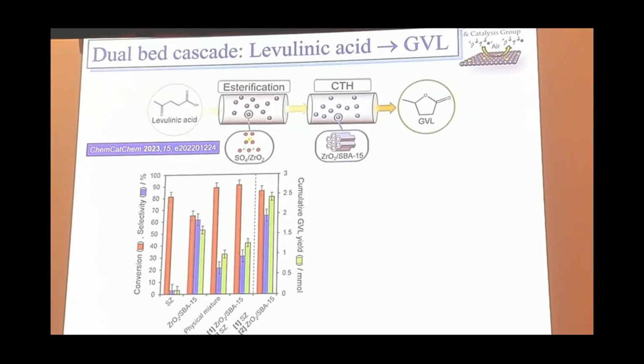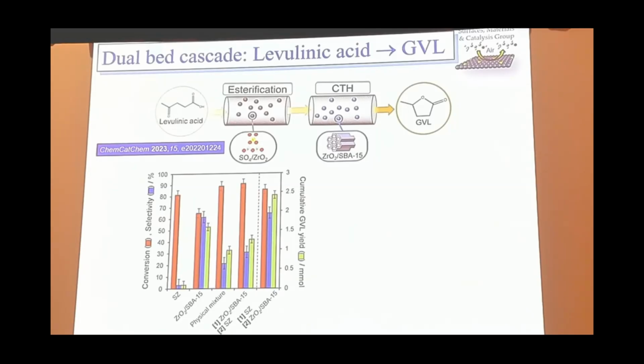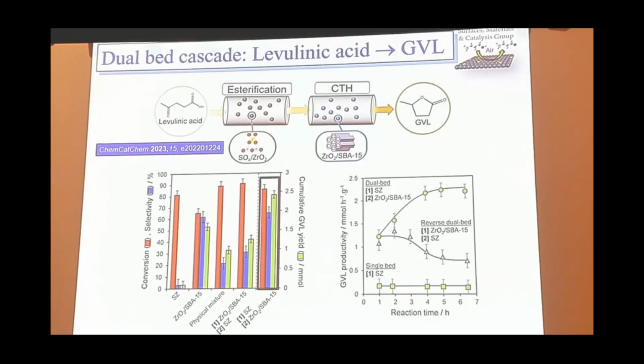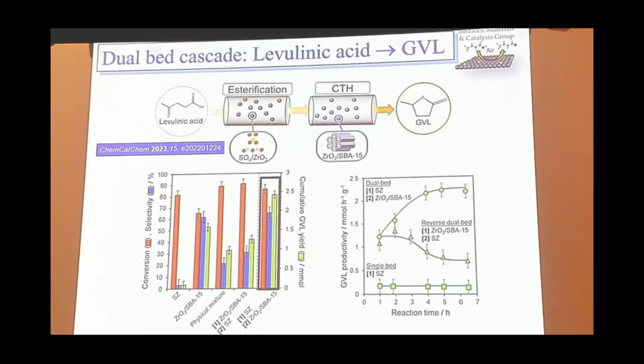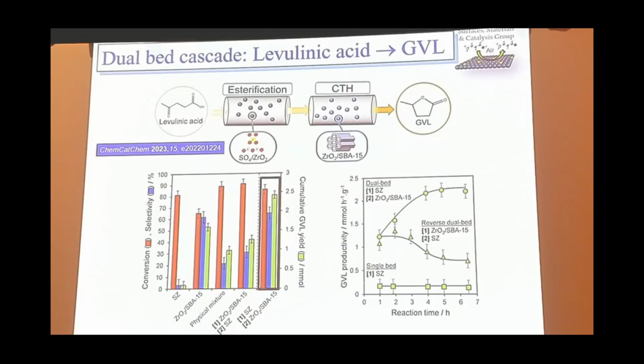Now, there's a few combinations here, because what actually did matter was which way round you had the bed. Logically, you think, yes, you have this esterification bed first, it should improve things, and we really demonstrate that. So the system in sequence, we say here, is sulfated zirconia first, followed by our zirconia SBA-15. You can see you get the highest yield of gamma-valerolactone. So the selectivity to gamma lactone is optimum for this system. If we do look at, for example, a control, a reverse bed, you can see that is poor. And a single bed as well, just sulfated zirconia, is also poor.